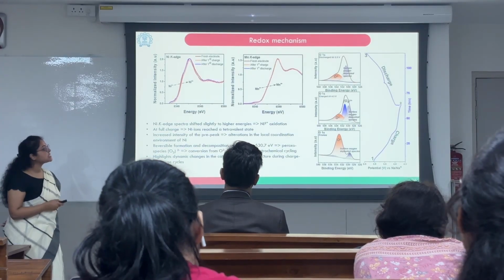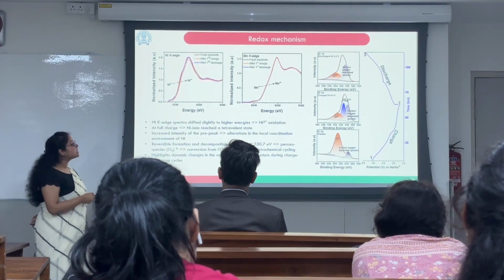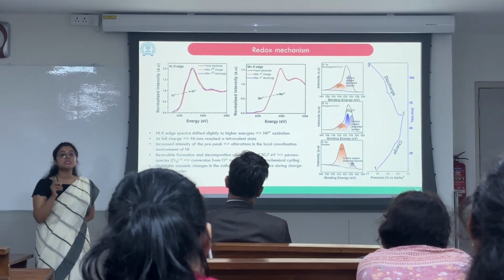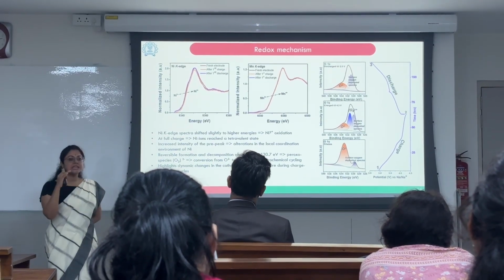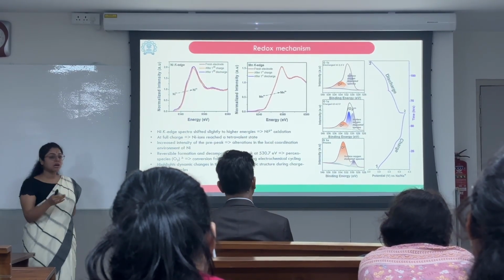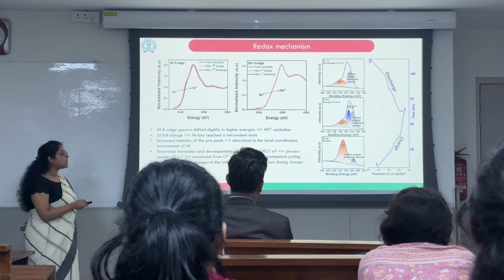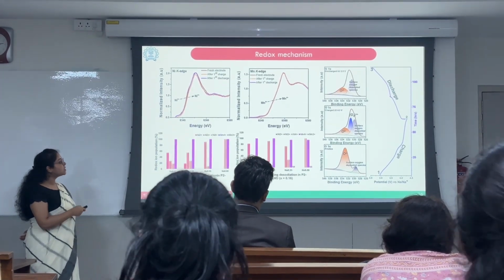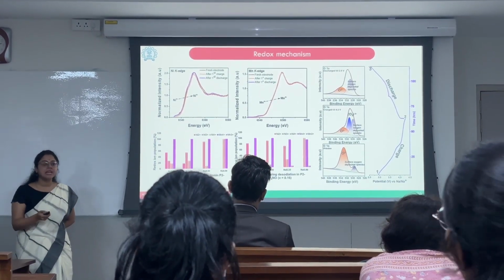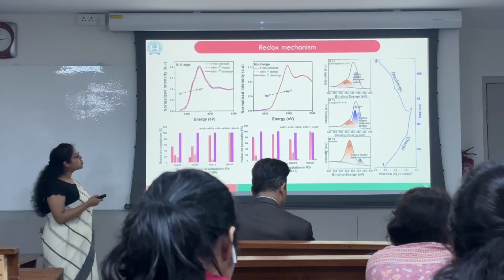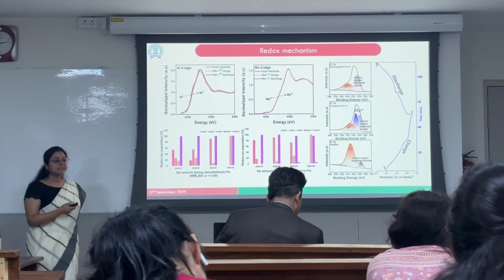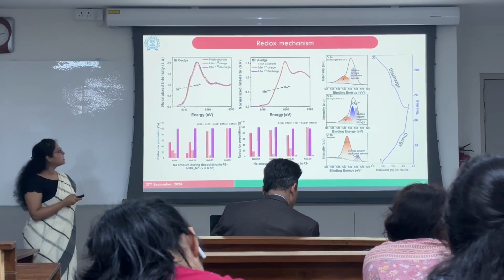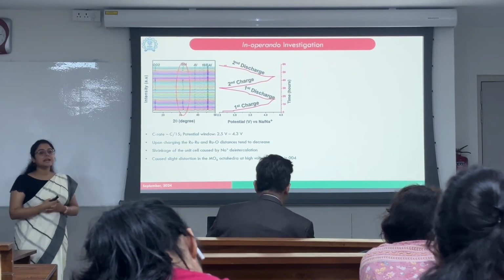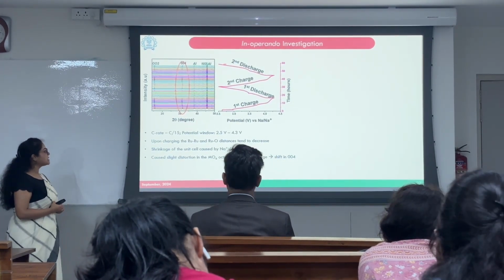Through the XPS analysis, we found that indeed peroxo-like species have formed when the material has been charged, and the XPS has been taken at the charged state. And this was further validated through the redox population calculation theoretically as well, which shows that nickel is active as well as the oxygen.